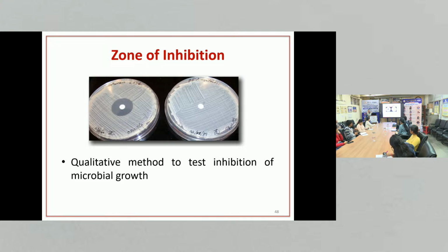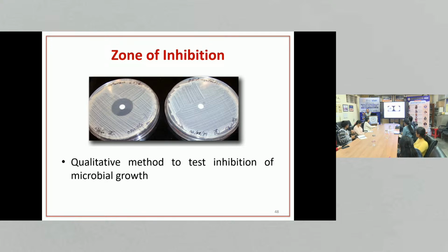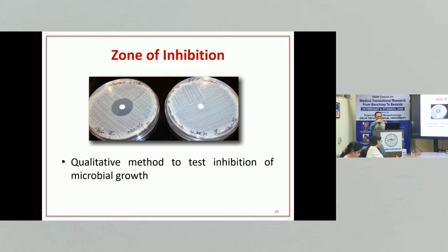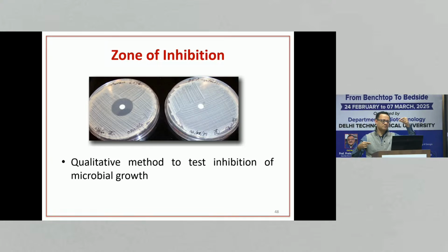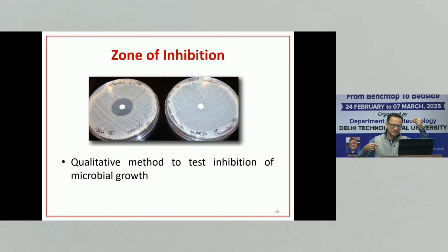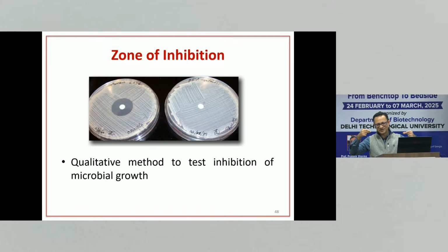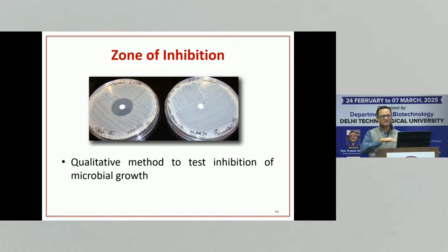But you cannot see it, right? Because you cannot see bacteria with naked eyes. So you are just putting all the bacteria solution on 2 plates. You put a piece of your catheter and your control catheter, let it sit in the incubator at 37 degrees overnight, and come the following day and see the zone.